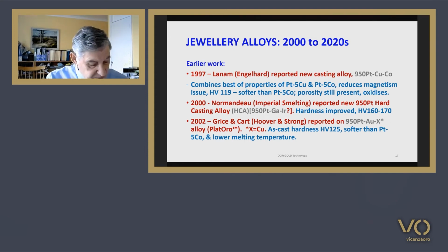A further alloy development was presented by Grice and Cart in 2002, where the development of a platinum gold X alloy, Plat Oro, is reported as an alternative to platinum 5% cobalt. This has an as-cast hardness of 125 Vickers, a little softer than the platinum 5% cobalt alloy, but it is non-magnetic and has a lower melting range of 1590 to 1629 degrees Celsius. Grice has since reported that the Plat Oro alloy is actually a 5% gold copper alloy, but is no longer commercially produced.